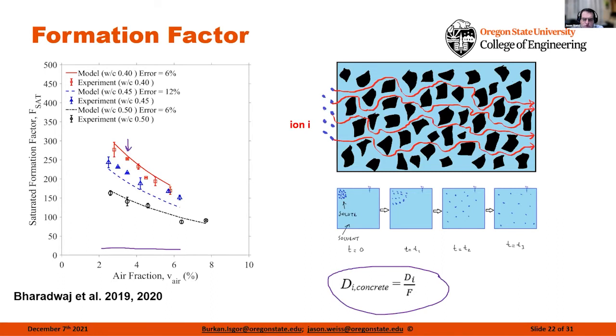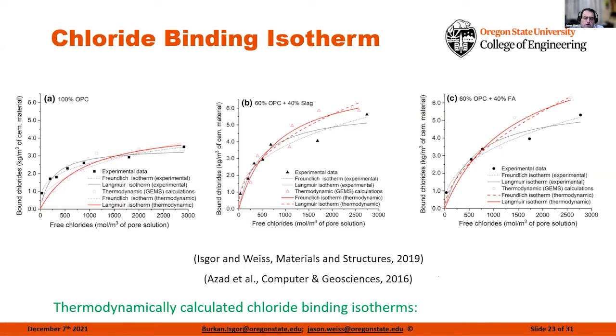So I can get a diffusion coefficient. I can then start to predict how many of these ions are going to bind to the system as they start to move through the system. So what you'll notice here is the black are the actual experimental data that we've actually measured, and the red is completely simulated data saying if we know what the chemistry of the system is and we know some basic rules or some basic principles on the binding that should take place, this is what we would predict from the red lines.